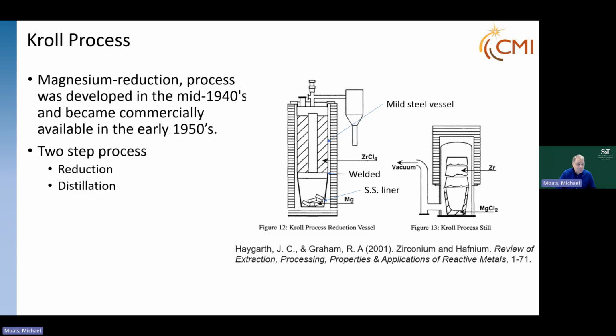So the Kroll process was developed in the 1940s, really for titanium. Titanium and zirconium are usually reported in the literature together if you're reading reviews. So the technology is very similar. And so what happens in the Kroll process is it's a two-part container that's put inside of a furnace. It's called a pit furnace because it's usually dug into the ground. Zirconium tetrachloride is loaded into the top, and there is a channel or a tube that comes between the bottom half and the top half.